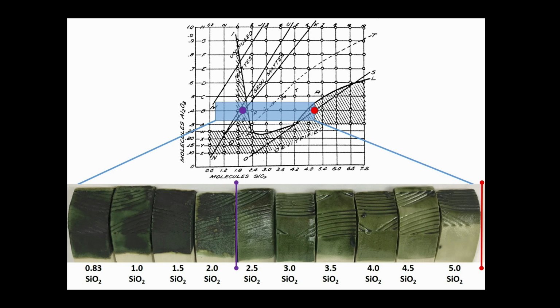So we did a first firing of tiles that had a 0.4 alumina ratio, and then we did increases of 0.5 silica, beginning with the lowest silica we could use. This is the first set of tiles plotted into the UMF. And I hope you can see it well.